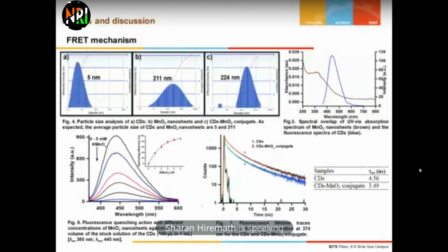the lifetime study of the CDs and MnO2 conjugate. We can see the CDs have a lifetime of 4.56 nanoseconds, whereas the CDs-MnO2 conjugate shows 3.49. This decrease in the lifetime proves that the CDs and MnO2 have undergone the FRET phenomenon.